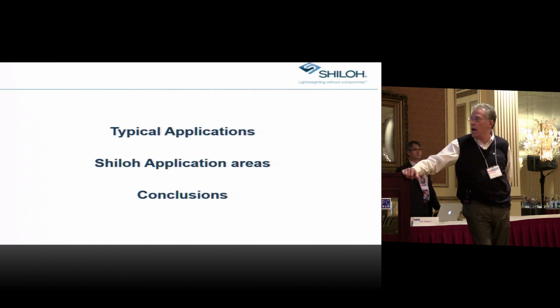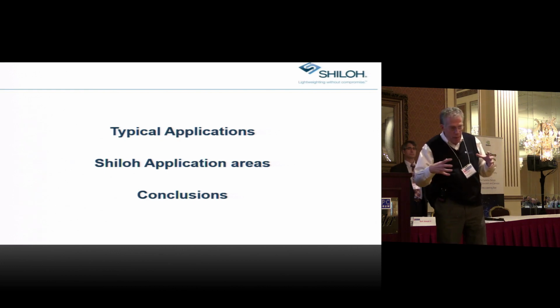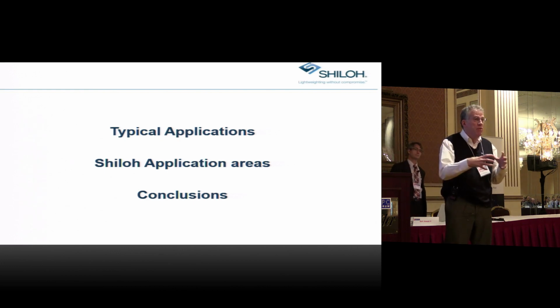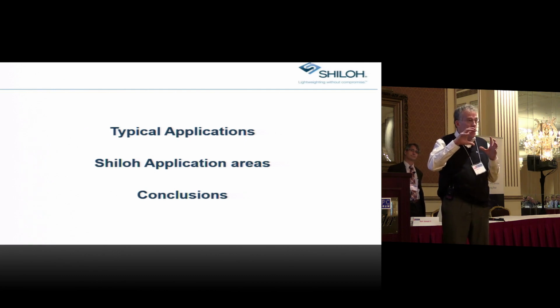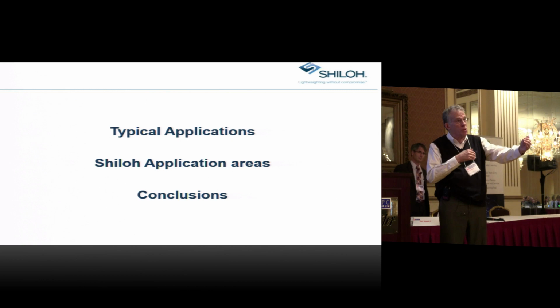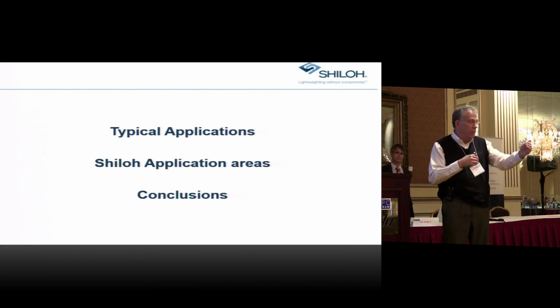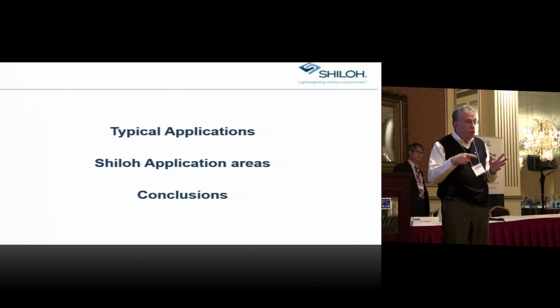So it's useless, wasted time. But the most important thing is when we're taking these castings and putting them in structural applications, the thing that's critical is that a normal aluminum casting maybe has an elongation of maybe 1% or 2%. So that means it's going to go through its elastic deformation, come up into the plastic zone, and move from plastic to failure very quickly. It's going to shatter. So if I'm looking at a frame of a vehicle, I don't want the frame to shatter. I want to be able to design the collapse and the absorption of the energy of that component as the event is taking place, whether it's a half frontal crash, a side crash, a rollover, whatever it is.